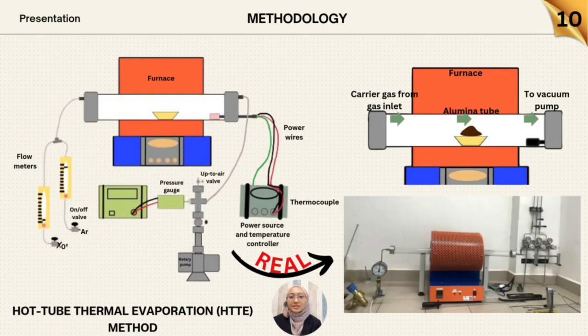This slide shows the hot tube thermal evaporation setup, where a controlled environment was maintained using alumina tube, thermocouples, and gas flow meters. So this precise control allowed us to achieve consistent activation conditions, ensuring reproducibility across samples.